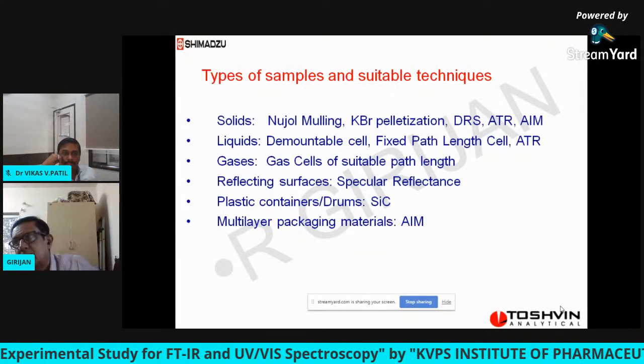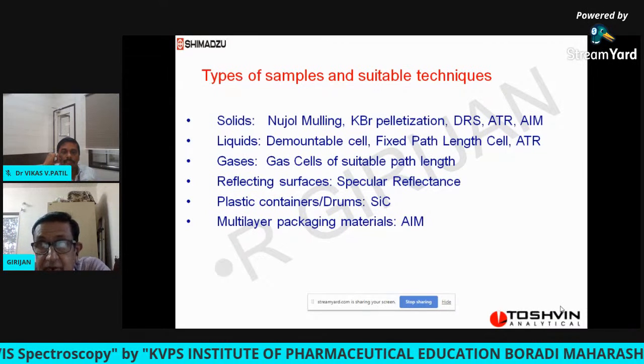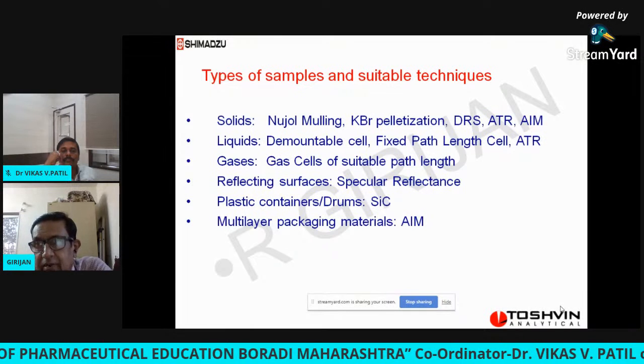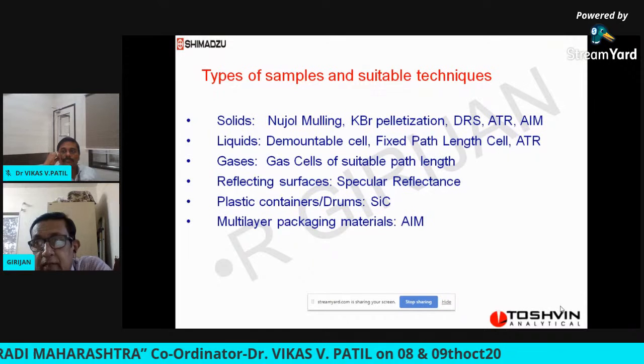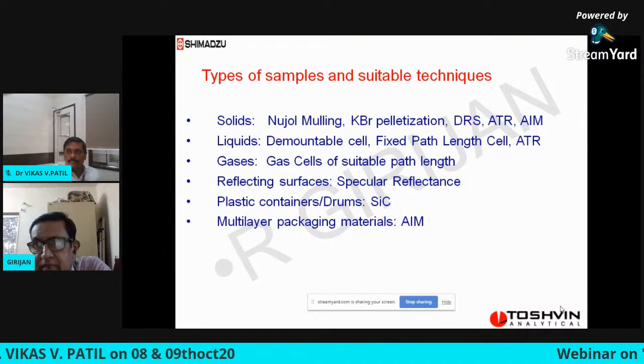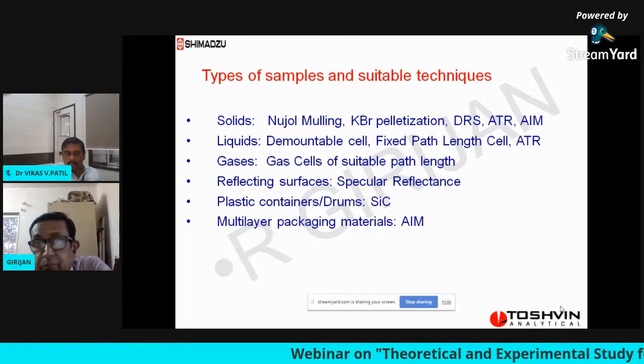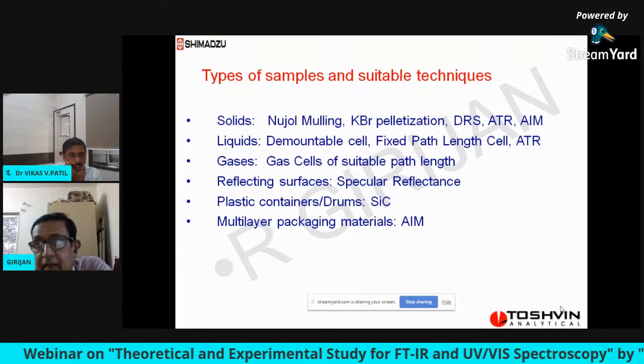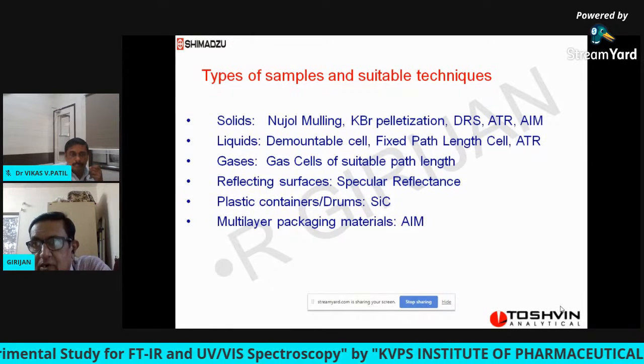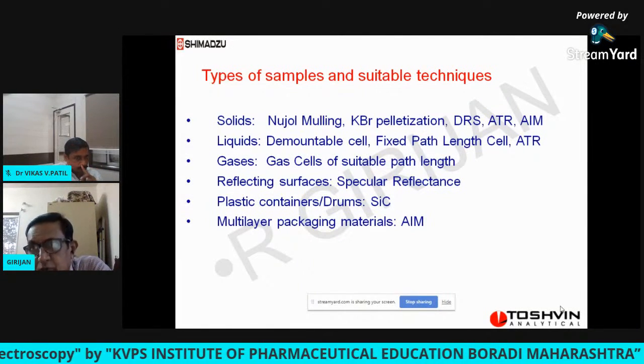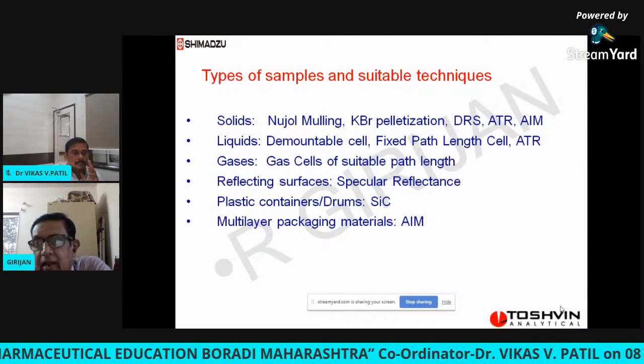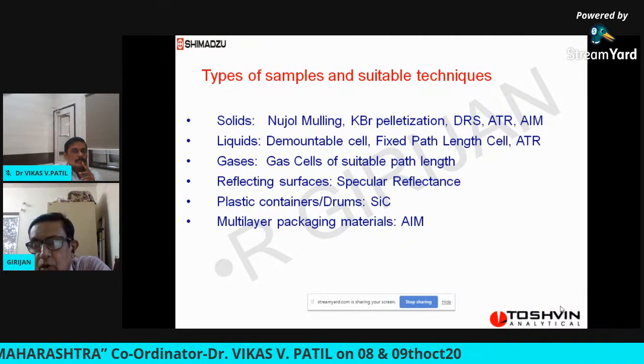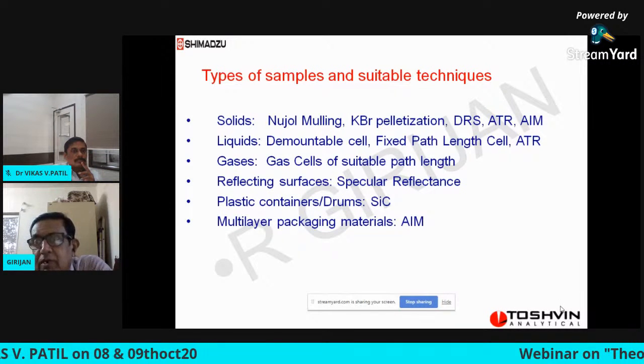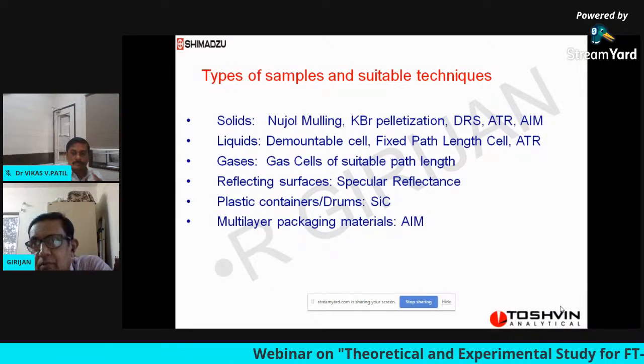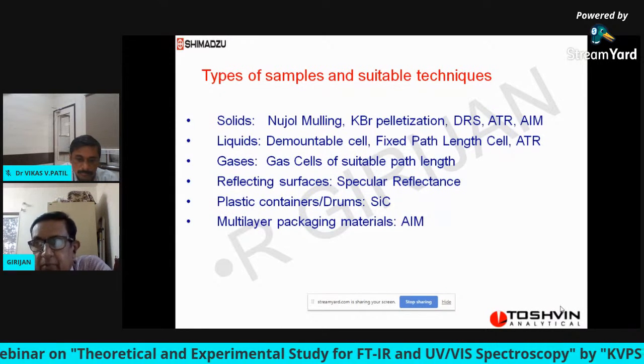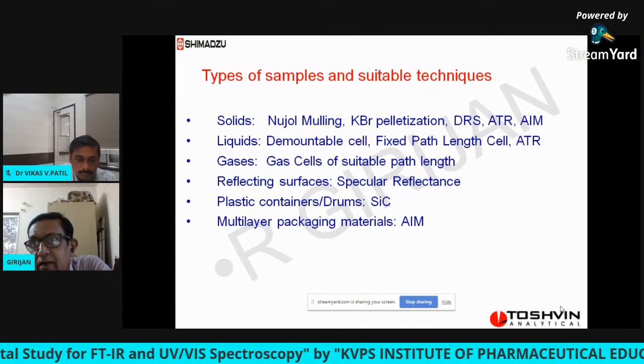KBr pelletization was also a very important technique till recently, especially in the pharmaceutical industry. Pharmacopoeias were recommending the KBr pelletization method till recent times, but now there are other accessories available. KBr pelletization means you take about 1 to 2, maximum 2 to 3 milligram of your sample, and mix it with 100 milligram of pure dry spectroscopy grade potassium bromide using a small pestle and mortar. Then this mixture is put in a die, and the die is connected to a vacuum pump, and you apply a lot of pressure, normally about 10 tons, and keep it for about 10 to 15 minutes. After that, we release the vacuum and the pressure, open the die, and if it is properly prepared, you get a 13 millimeter circular disc which looks like a piece of glass.